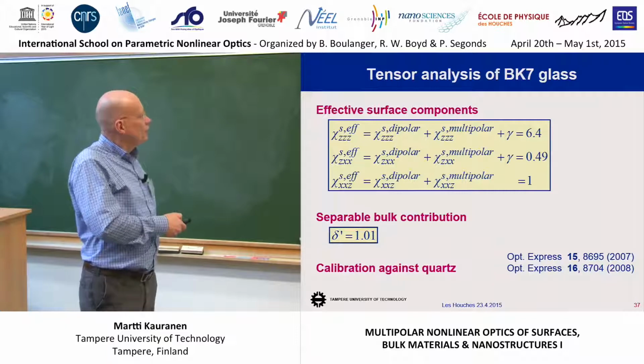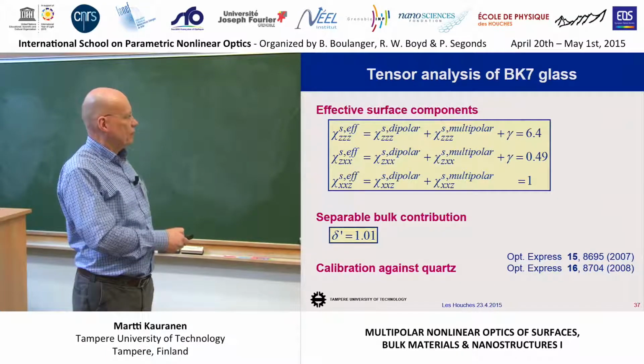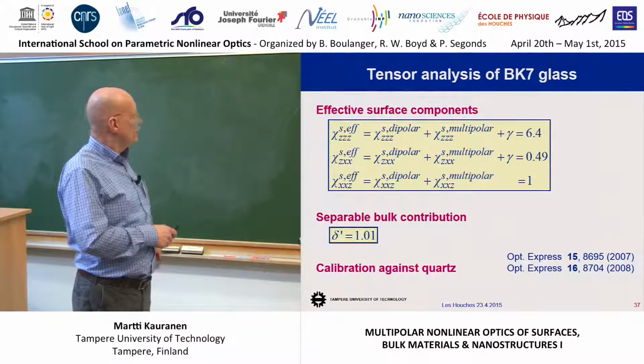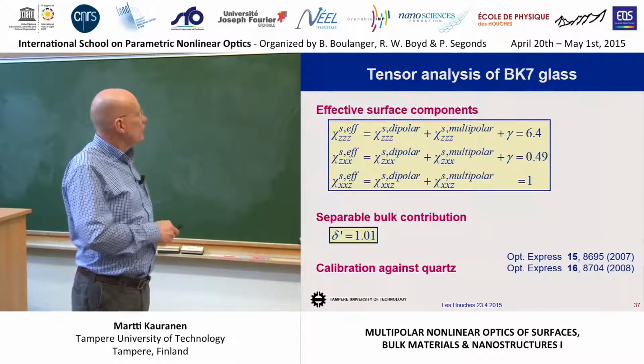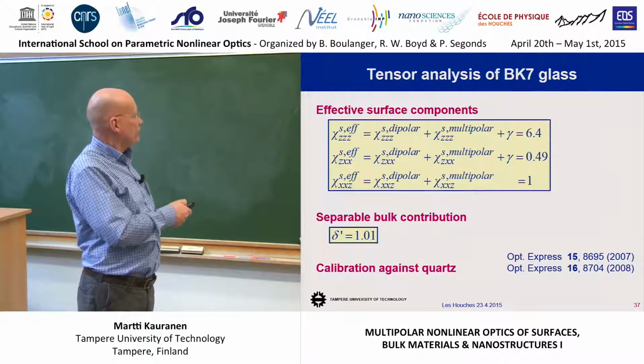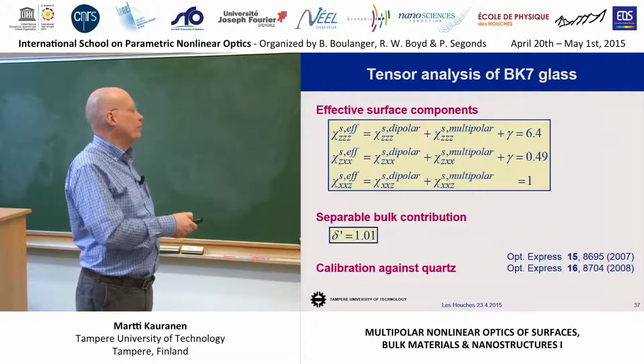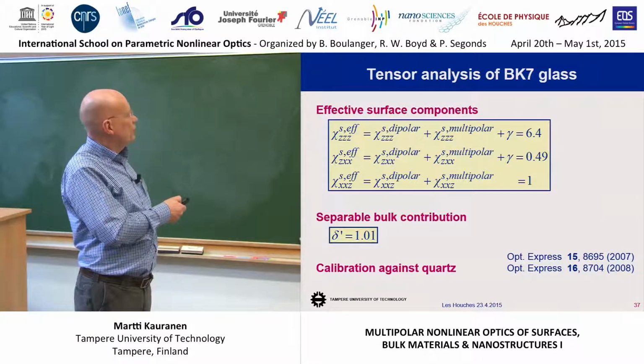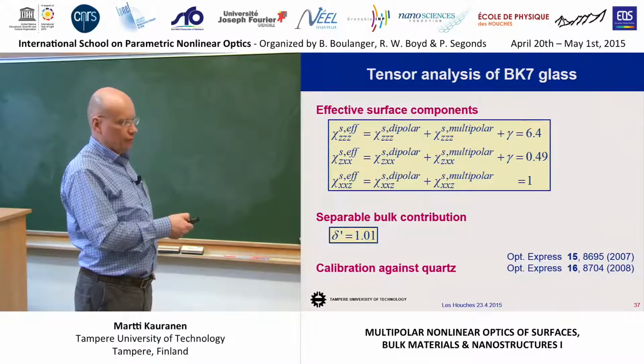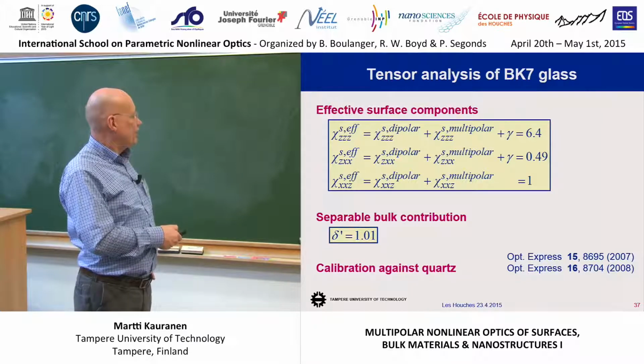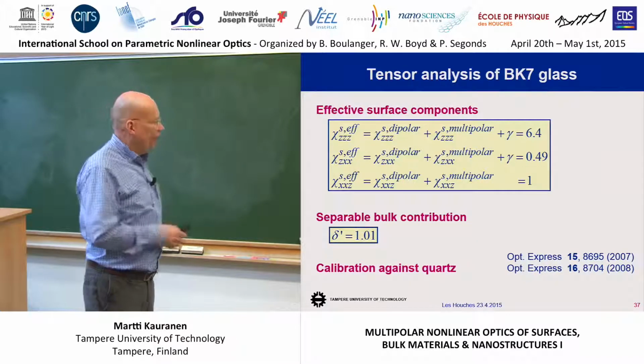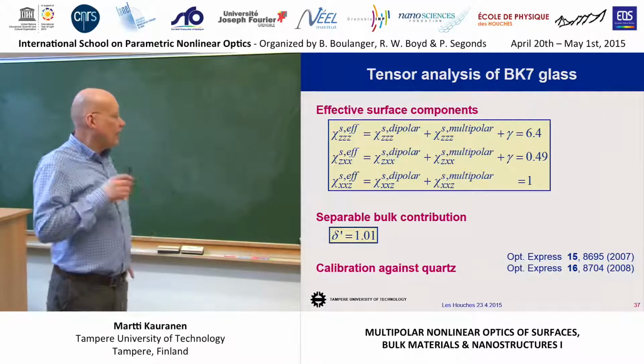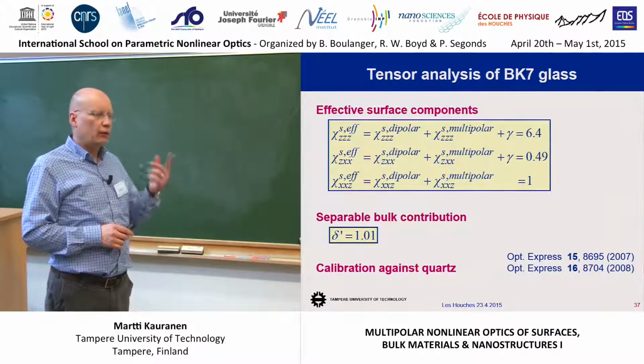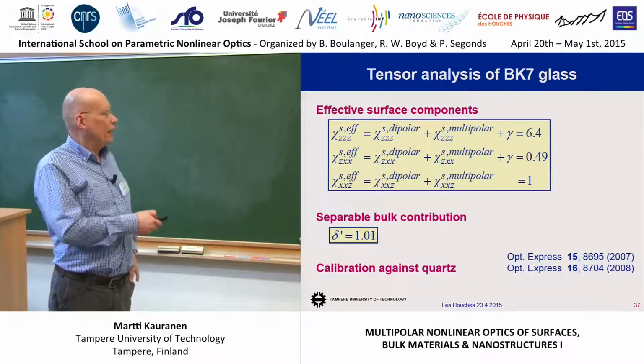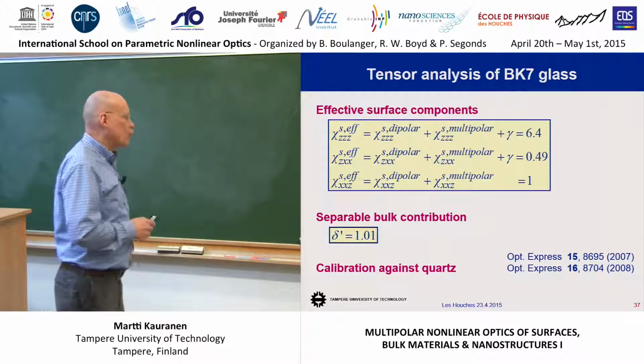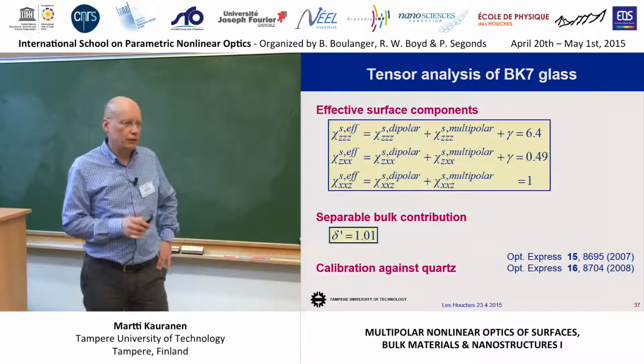We normalize the response to the XXZ component of the surface tensor. That's one. And then what we get here is that the ZXX component of the effective surface tensor is 0.49. I mean, let's say 0.5. And the ZZZ component of the surface tensor is 6.4. And then the bulk parameter delta prime is about 1. And then finally, what we can do is take all these results and calibrate our signals to a reference material which is crystal quartz. So we actually get numerical values for these components, and then we can compare those to earlier measurements or some theoretical models and so on.